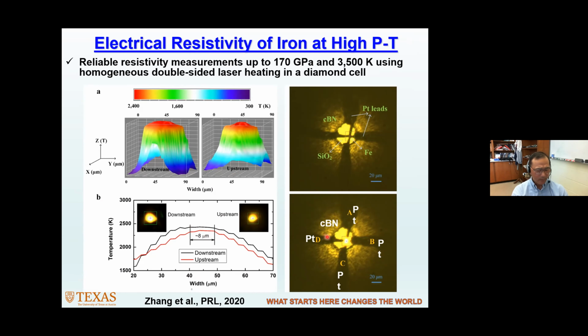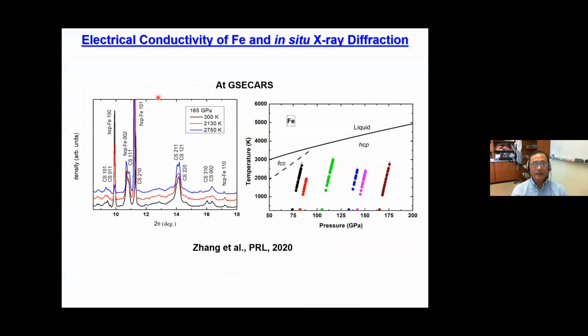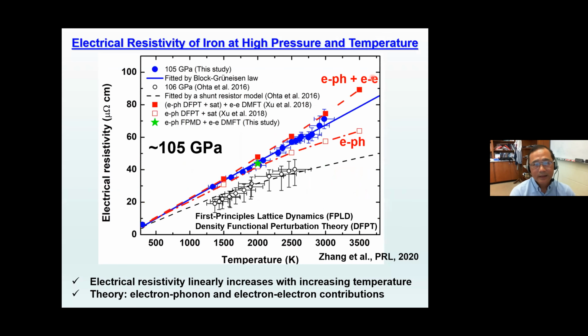fact. So another thing is to actually make sure that we are indeed measuring the sample from HCP iron and using in situ X-ray diffraction, and there's not much texture in the sample. So we actually conducted in situ X-ray diffraction experiments.